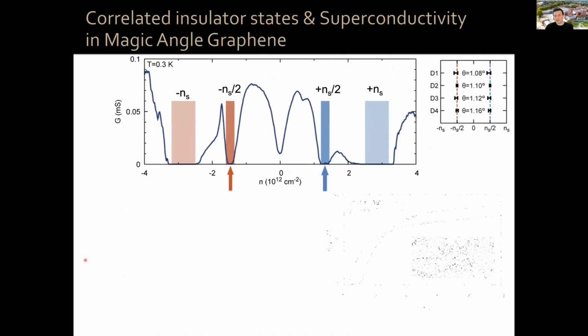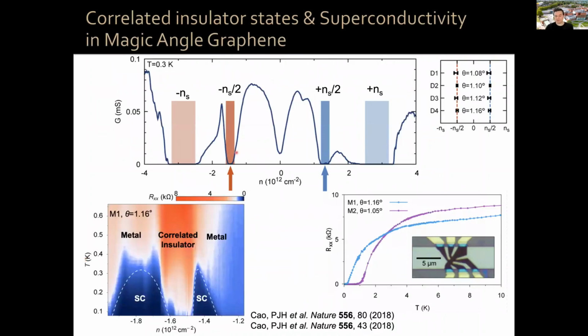A couple of years ago, to our big surprise, when we made devices at this angle, we observed correlated insulator states, which occur at 2 electrons and 2 holes per moiré unit cell. So we have single particle insulator states, but then we have correlated insulator states. Back then we called this half filling of the conduction and valence bands, but now we use different terminology. Basically this occurs for 2 electrons and 2 holes per moiré unit cell.